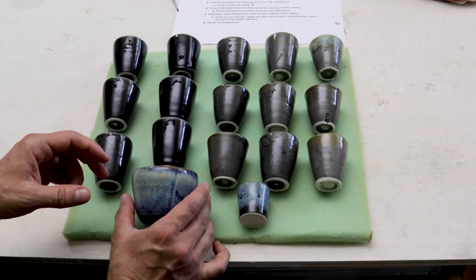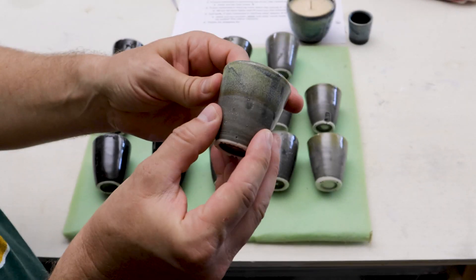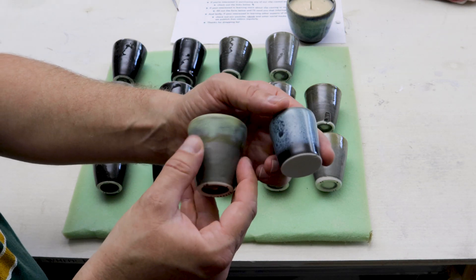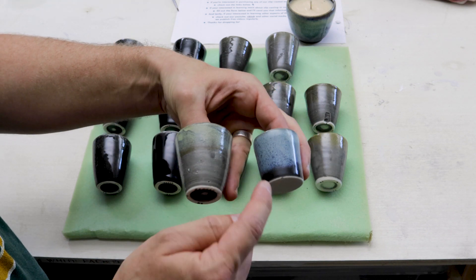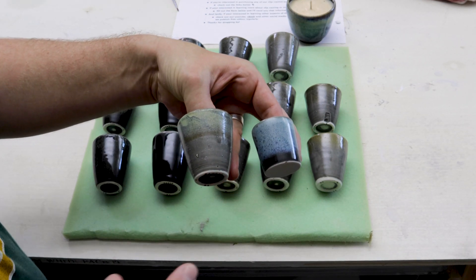Here's my original that I was trying to recreate, and here's one I recreated recently. As you can see, nothing on the array looks specifically like the original, although there's one that's close. This is the one that worked — kind of. Look at the discrepancy: you're getting a lot of that same texture, you can see that rutile underneath hinting blue, but the difference is the base glaze. This is obviously a light gray and the original was a dark black.